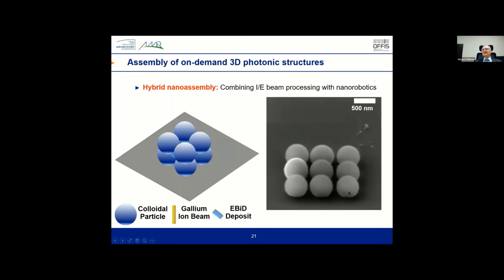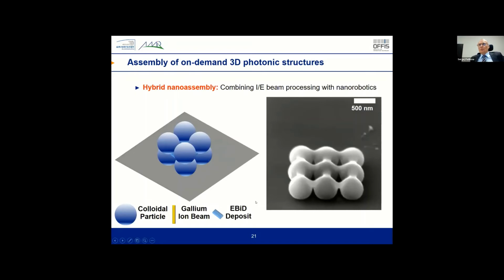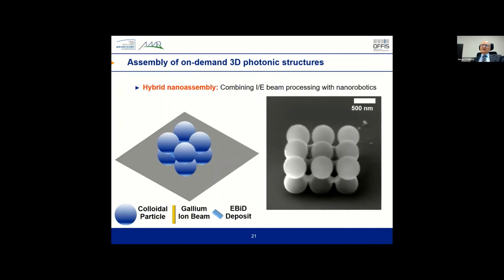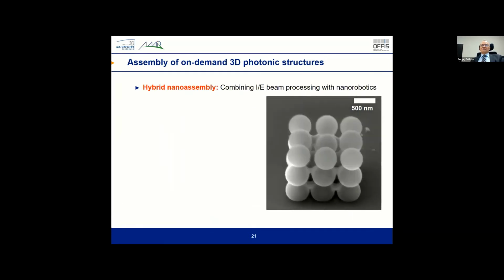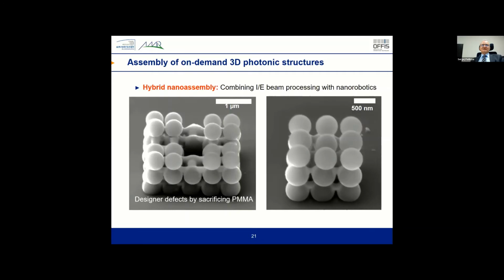Here you can see this in reality. So the first layer of nanoparticles, robotic handled obviously, then bonding, then FIB fabrication, milling of the surface, here the second robotic application, and so on and so on. But the most important, what we implemented recently, as I mentioned, designer defects by using different particles, right? Because, for example, if you use particles made of silica and made of PMMA, then after your assembly, you can selectively etch, for example, PMMA particles, and you can get assembly on demand of any possible 3D cubical photonic structure. So this is really an interesting result.